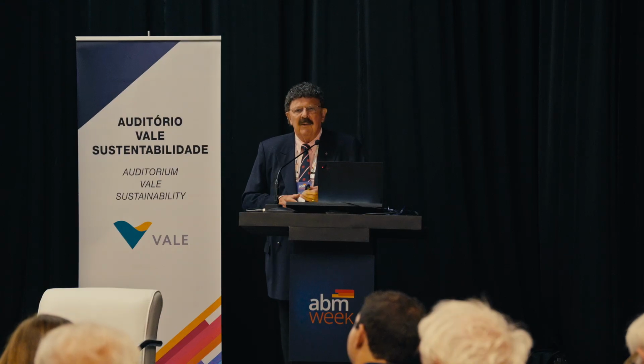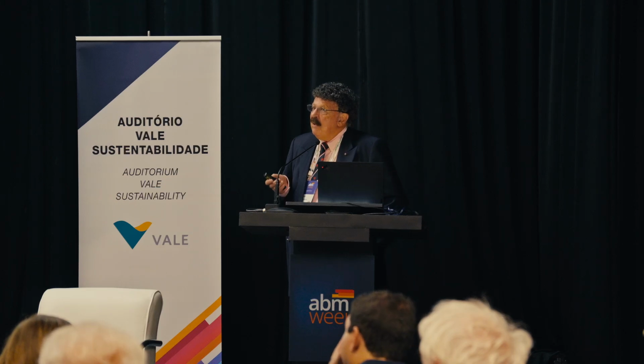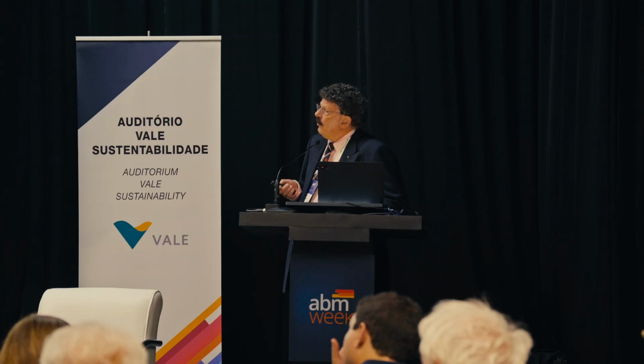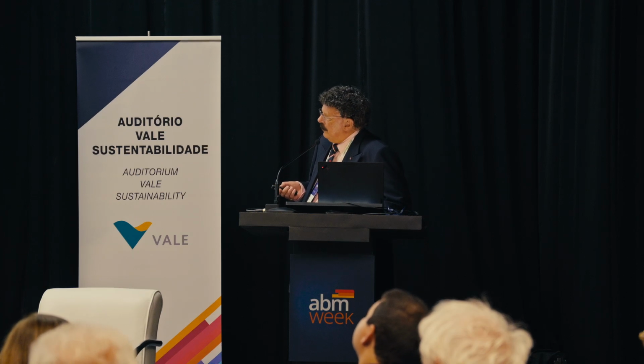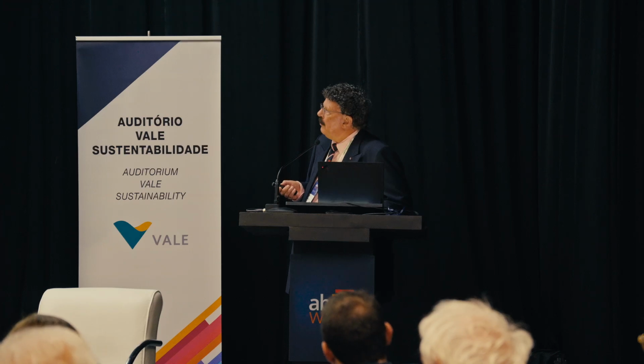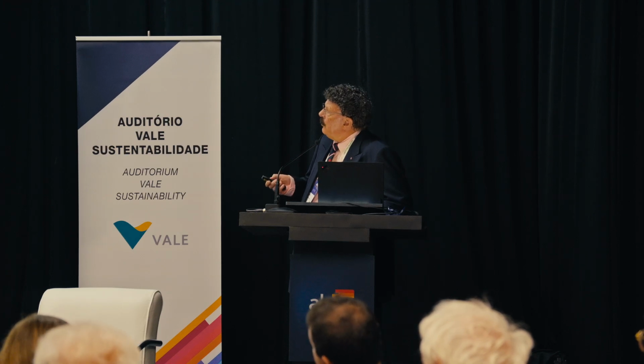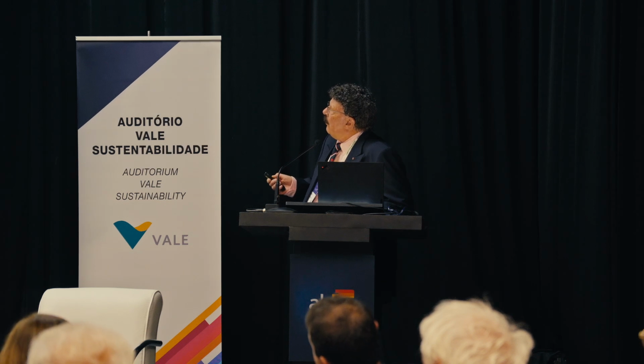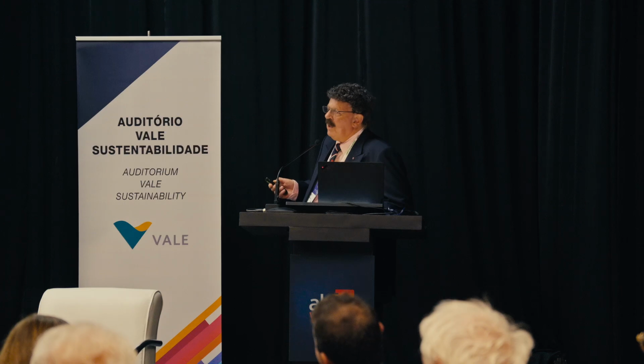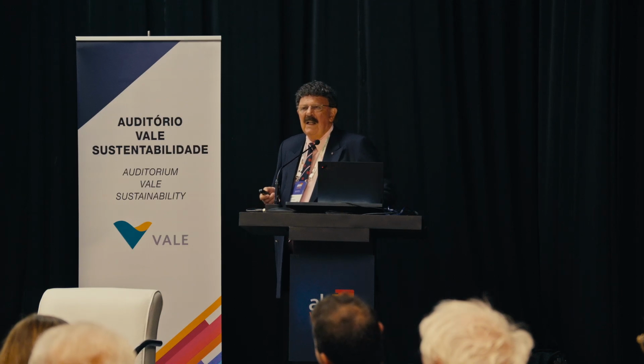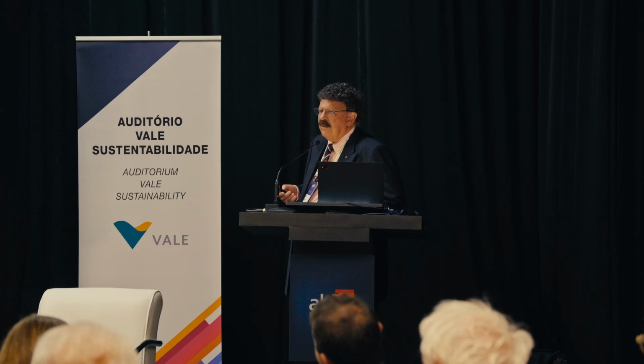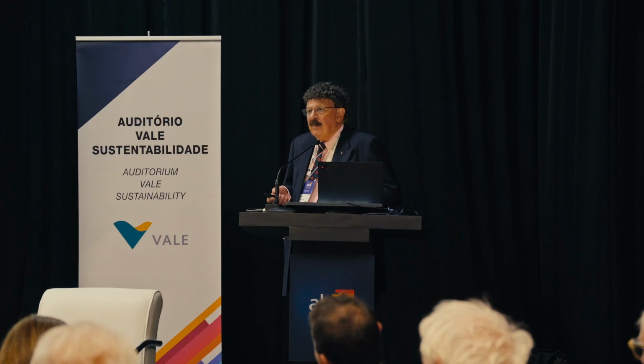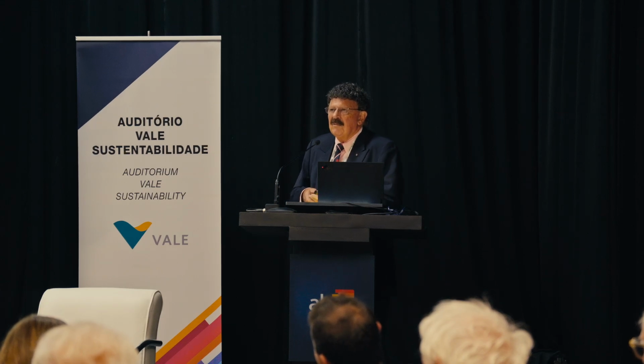We've looked at some other aspects here, and this is basically working with Marc Meyers. We looked at very high strain rate conditions. Now, if it's good at cryogenic temperatures, it should be good at high strain rates. And this is work done with Shiteng Zhao, who I think you know here. This was using Hopkinson bar, and we looked at this particular high entropy alloy, and we don't measure toughness here, but the absorbed strain energy is far higher than any other material that we've looked at before. So this is, again, a feature of these materials. They have very, very high strain rate fracture resistance.